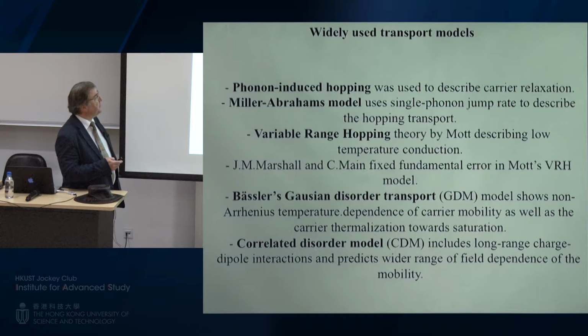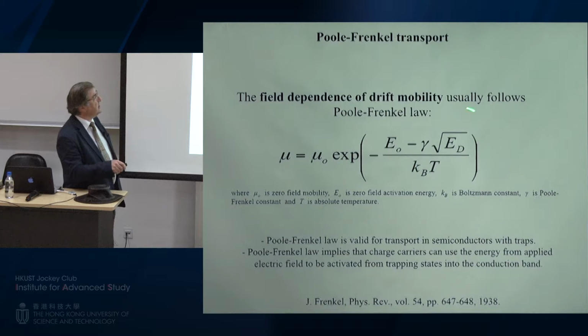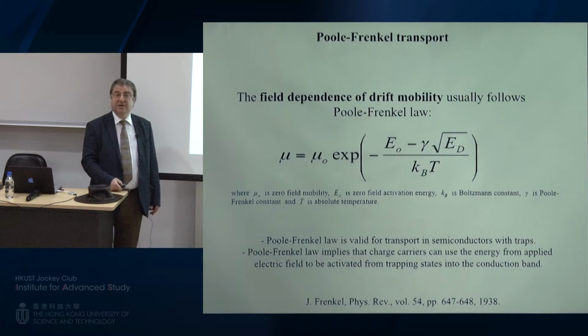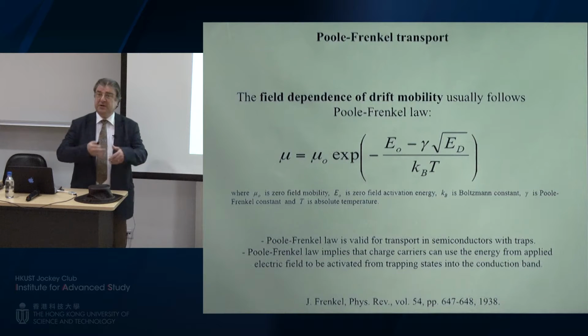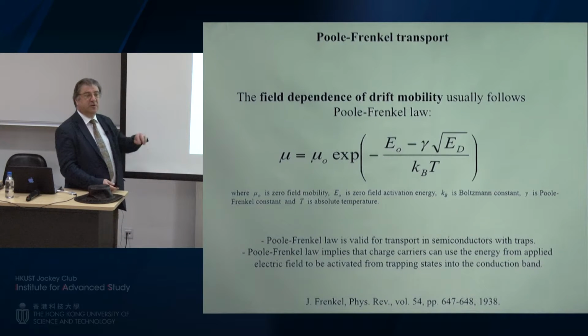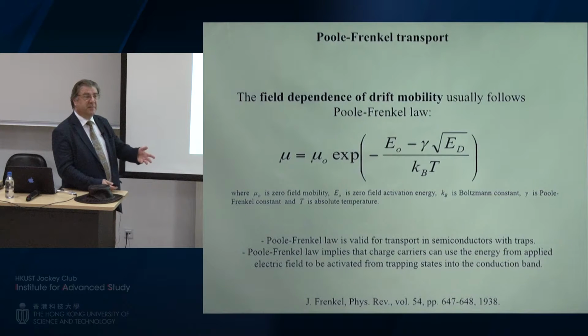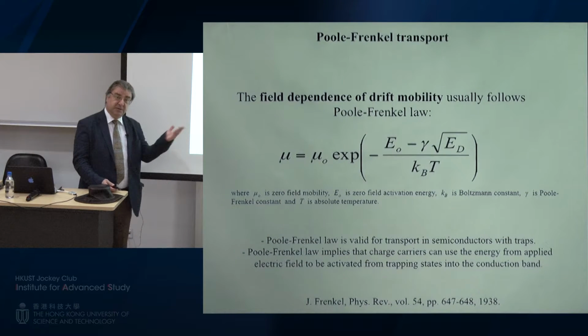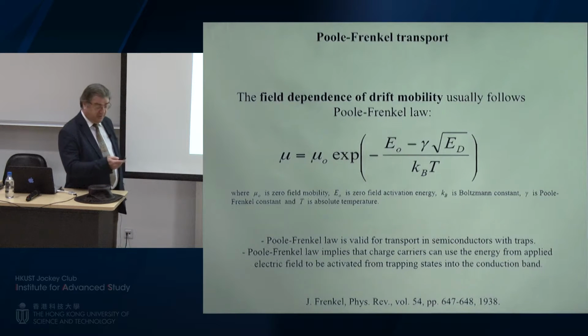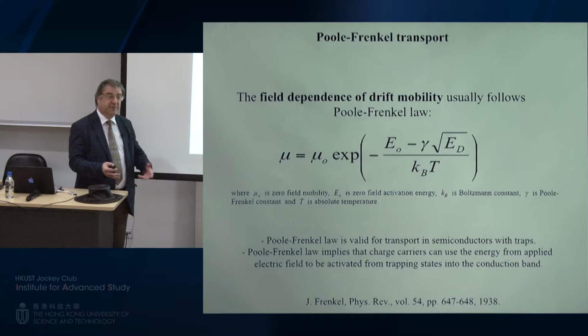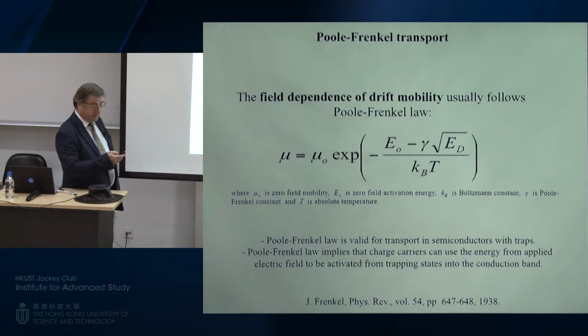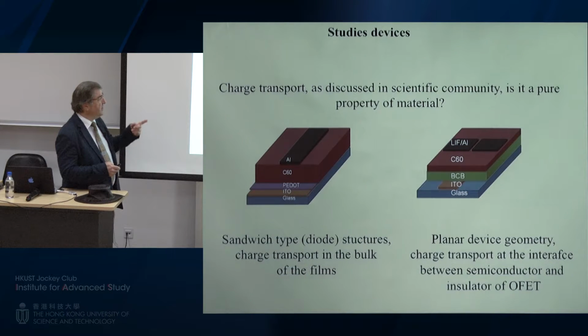I will skip these details, but this ends up in what we call Poole-Frenkel type of field-activated and temperature-activated transport, which acts exactly opposite. Normally, in a good semiconductor or a metal, if you cool the system down, the system gets more conductive and has more mobility. In our systems, if you heat them up, the system gets exponentially better in conductivity and mobility. This is something which still comes from the disorder. And with such a huge disorder, we can check these mobilities very nicely with a diode configuration or transistor configuration.